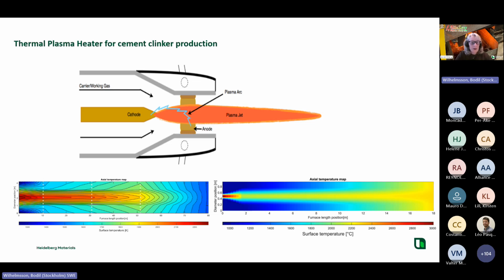With this in mind, we were a bit anxious that we would not be able to get the high temperature of the plasma plume to the material. But theoretical tests show that if we tilt the plasma and if we add particles, then this will change, because in a conventional fuel burner you have all the particles, which give quite a high radiation. But in a plasma with CO2, it's only a hot gas, there are no particles, so the radiation is quite low.